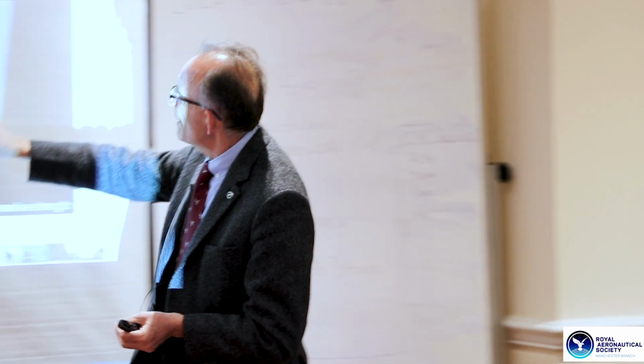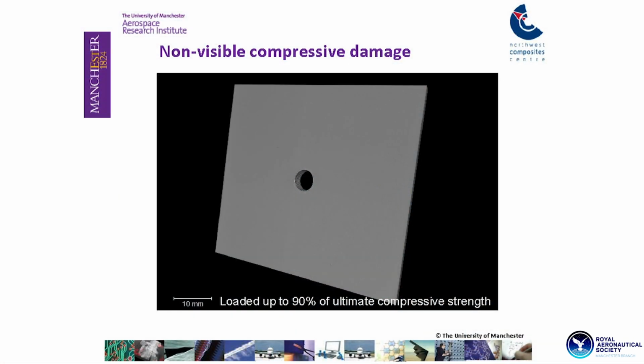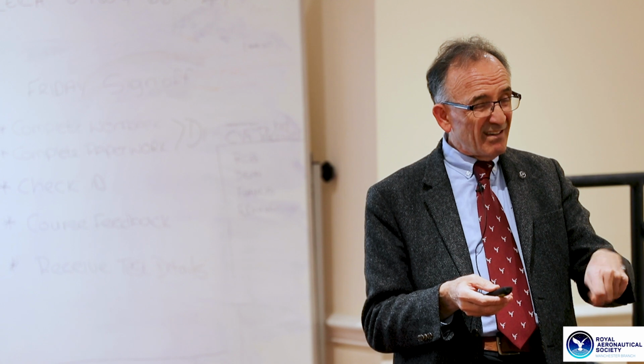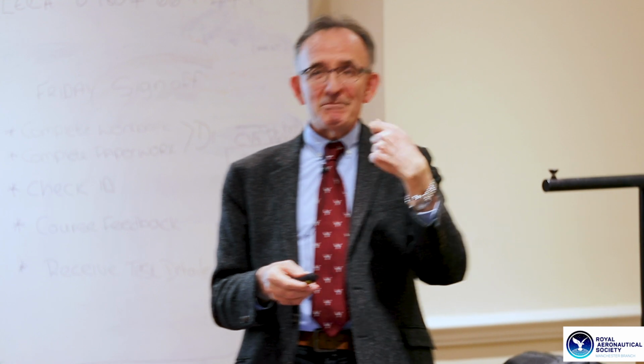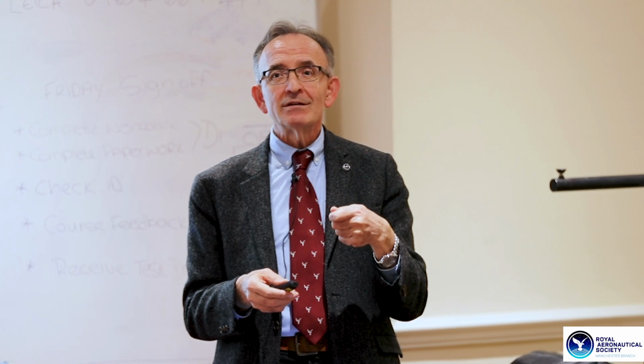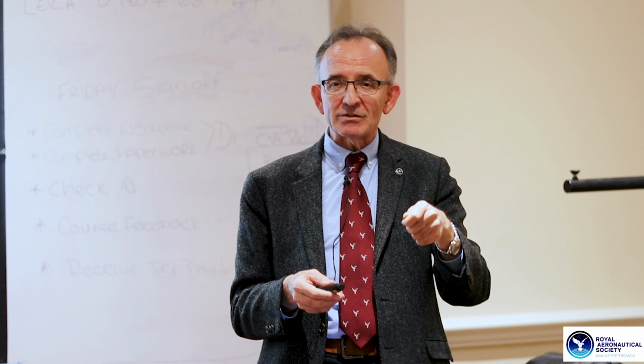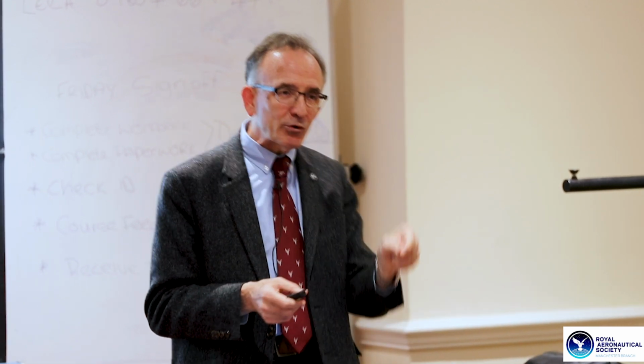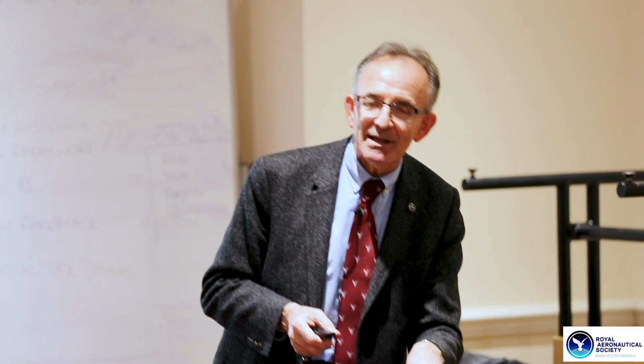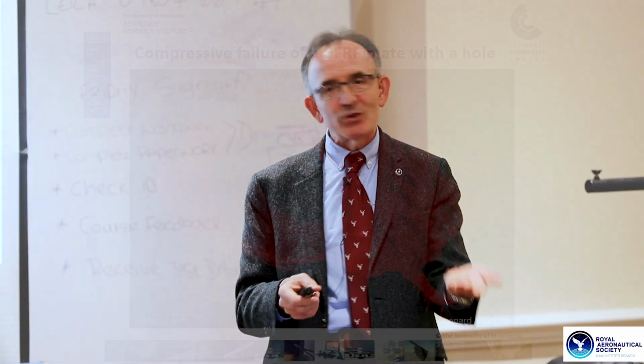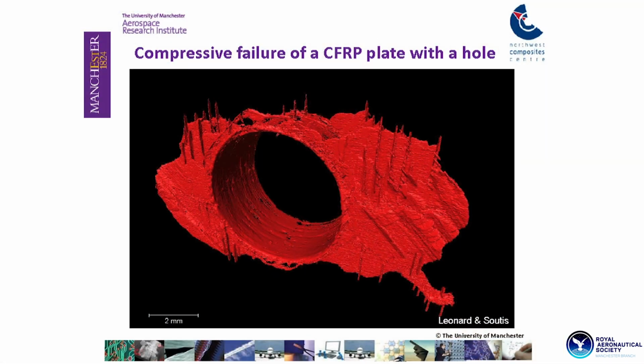We don't see any damage. We might see some few micro cracks there, but probably they were introduced during the drilling process of the hole. Again, if the operator that drills the holes is not careful, and I've been to factories where I have watched the technical people drilling holes, and they create local delaminations, and then the guy behind them with a pot of resin comes around and fills the gaps up with resin, and I tell them, sorry mate, it's not going to work. Already the laminate has been delaminated. And this is what's inside.